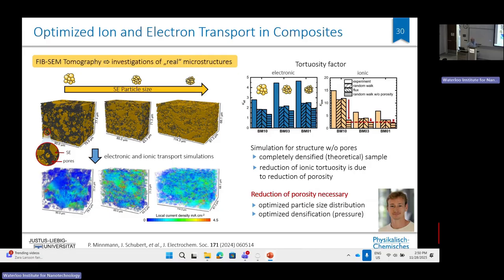And those without a pattern here, this is for electrons, this is for ions, those bars without pattern are the measured values. And they are always higher than those calculated from the microstructure. And the reason is there are features in the electrodes that are not taken by electron microscopy: nanopores, grain boundaries. So there are more defects in your practical electrode than you can get from microstructure analysis. So that's another reason why electrolytes have to be excellent to overcome these microstructural issues. In principle, they should be better than needed because you always lose effective conductivity due to microstructure.